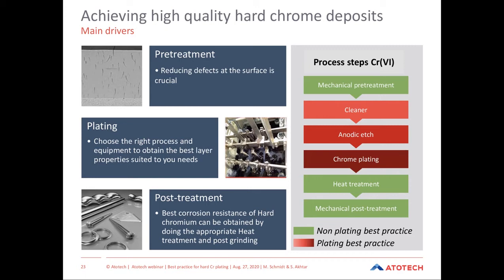And the post finishing is very important in order to remove possibly hydrogen which moved into the substrate for very high tensile strength materials. And it's very important to release the very high tensile stress of the chrome plating in order to achieve a good performance and a very good corrosion resistance. It's important to have very good results in each of the sections, because one weak spot in one of these areas can strongly impact the part performance and the final corrosion resistance of the plated part.